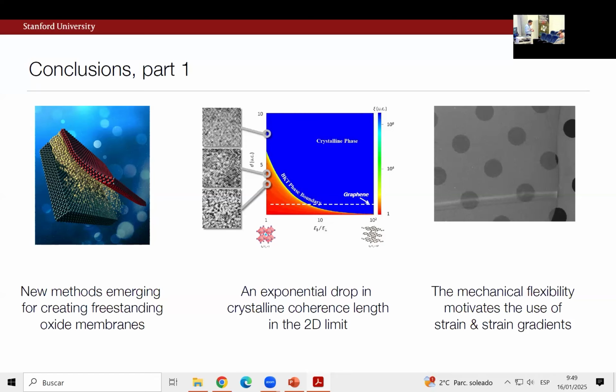Now, the same questions came up, and we spent a lot of time thinking and talking, even at one point with him. In that case, what they're doing is taking sodium layers and replacing them with larger and larger ions, organics and so forth. So there I could understand this gentle expansion, if you will. In our case, what we were thinking about is, can we cascade down? What is the strength of that interface energy scale? Can we break that down by analogy? I would speculate that this may not be the exact same numbers for every system, right? It has a lot to do with that interfacial bond. The other thing I should say is I think speed has a lot to do with this.